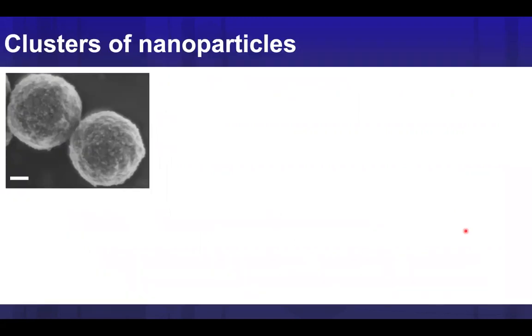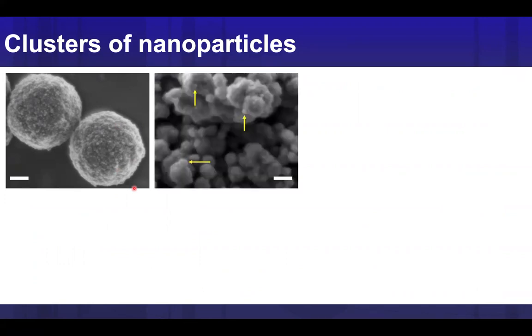And these are the first results from my group that I'm very excited to share. These are the first clusters that my students made. Very nice. And these are the latest ones. Here, we are starting to incorporate nanoparticles as precursors. You can see how these clusters are very homogeneous. The nanoparticles are very small. That is what we did before, right? Now we have this cluster that is not as nice, but still you can see that you have a homogeneous distribution of the nanoparticles in there. And then you have these big particles, where the yellow arrows are pointing to the ones that don't fit in there.